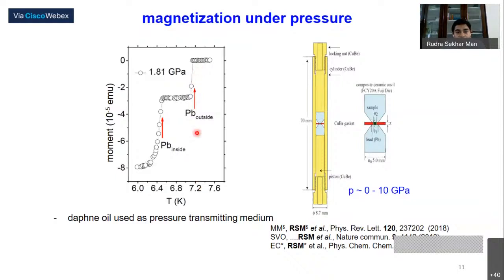Sorry, at ambient pressure, zero pressure, the phase transition is at 7.2 Kelvin. But if you apply pressure to the system, then your superconducting transition is reduced to a lower temperature. It's roughly 2 gigapascal, so 2 gigapascal is of the order of 10 kilobar. So now you can think for yourself how strong the pressure is.